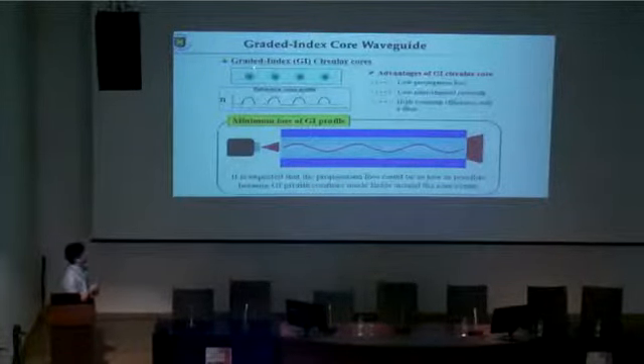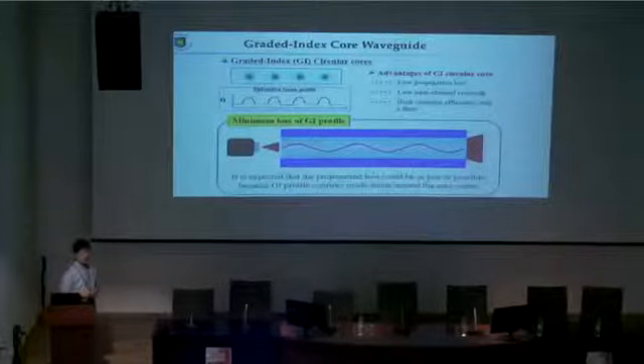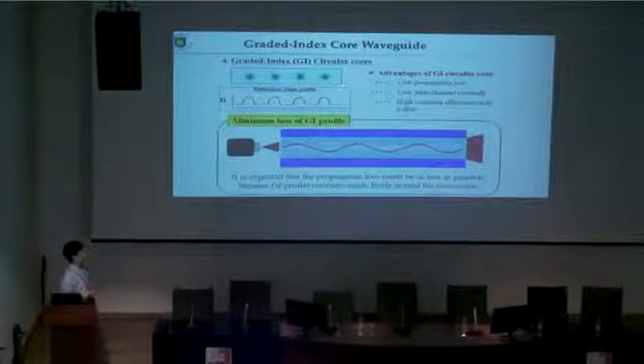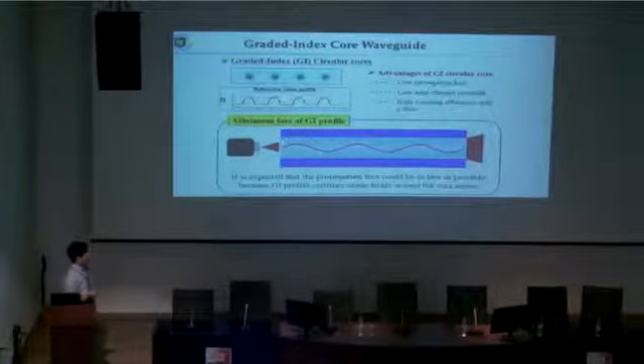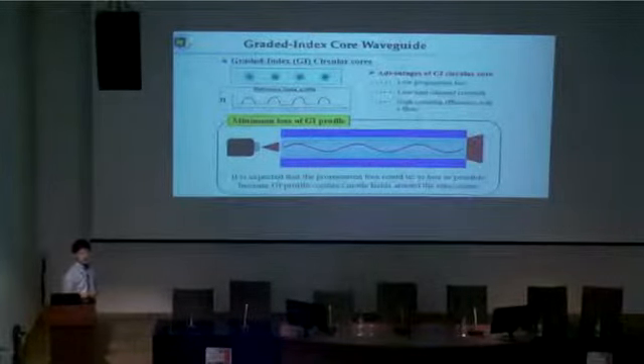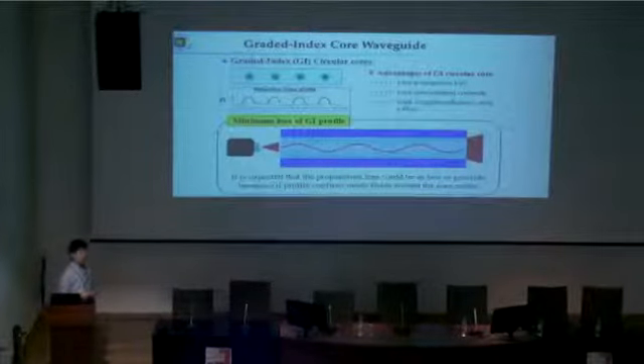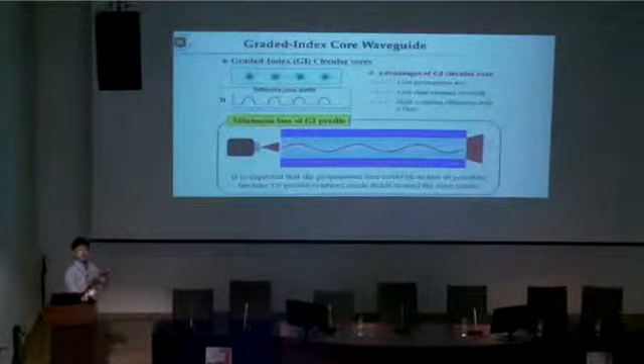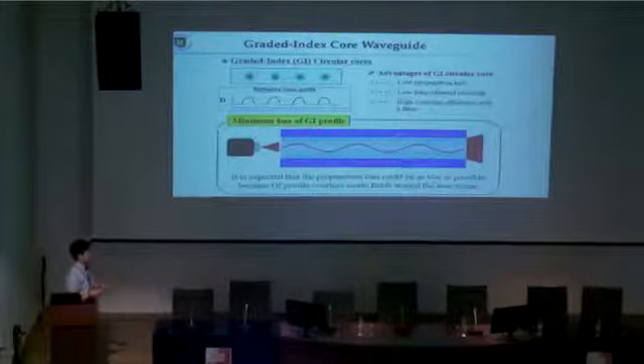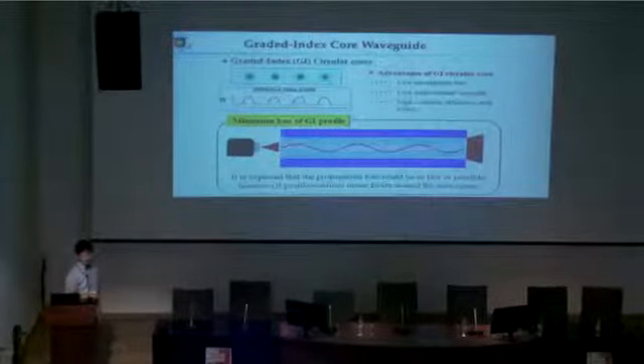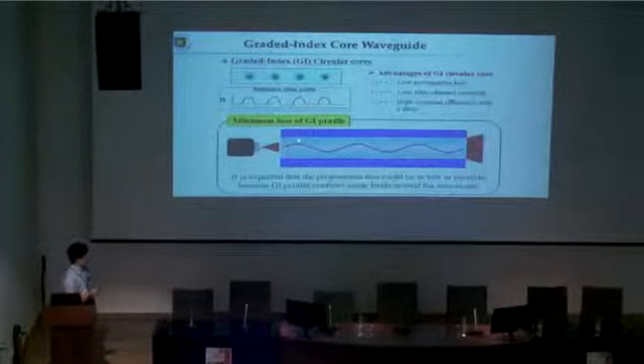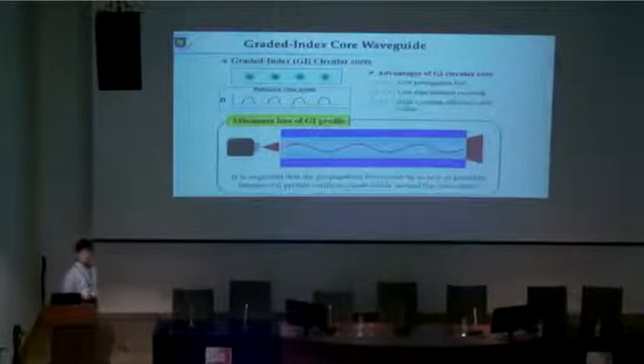That means graded index circular cores in a polymer. If we can realize these structures in polymer, we can expect these three advantages: low propagation loss, because in a graded index core, the light is no more reflected at the core cladding boundary, while refracted due to the refractive index distribution. And the light trajectory is like this sinusoidal one. You can see the light is not reaching the core cladding boundary. Therefore, we do not have to care about the core cladding boundary roughness.